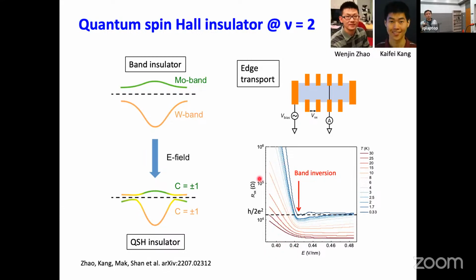Before band inversion, you can see that as we decrease the temperature, the resistivity just goes up, typically diverging. This is very typical of a band insulator. This is in log scale. After band inversion, you see that the resistivity first increases with decreasing temperature, but then it tends to saturate to a value about 85% of h over 2e squared, the quantum resistance. This is about 13.5 kilo ohm or something like that.